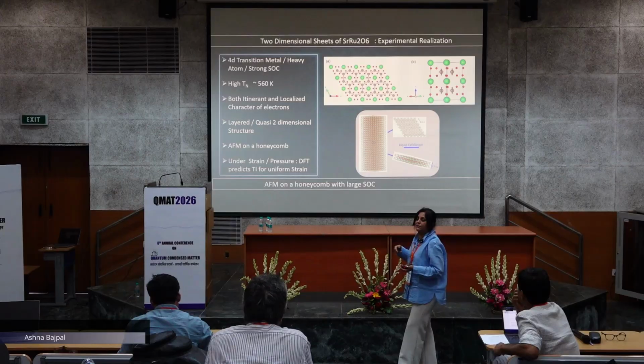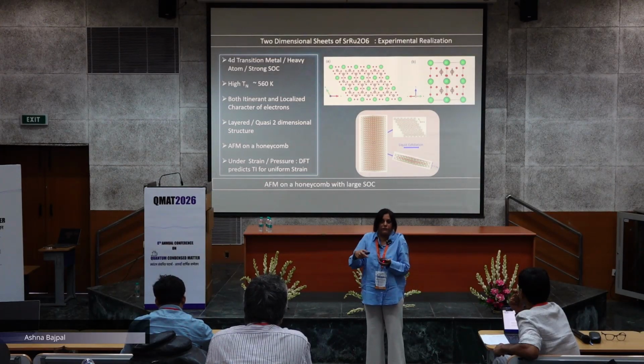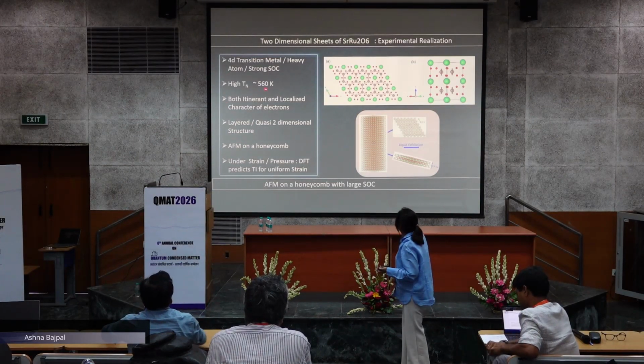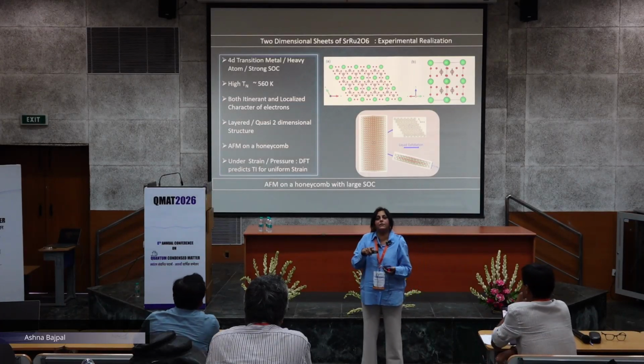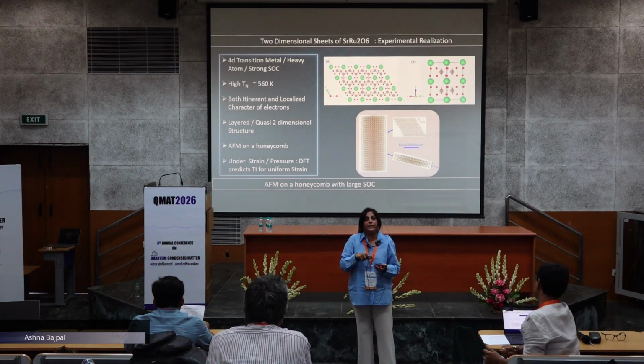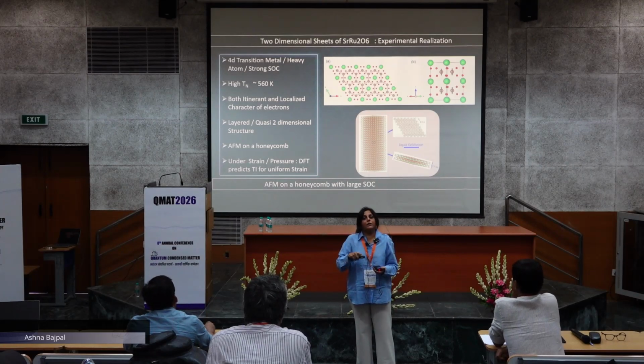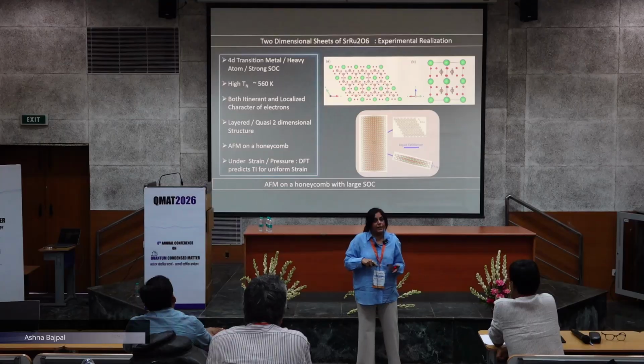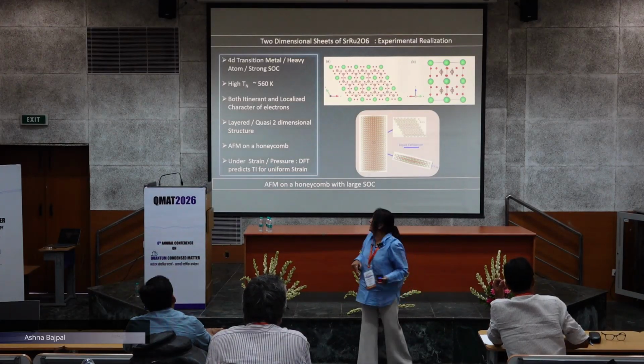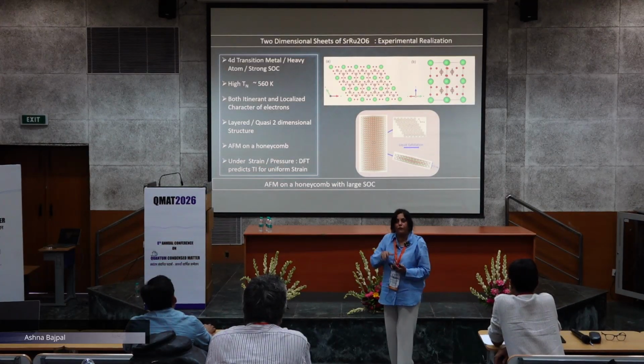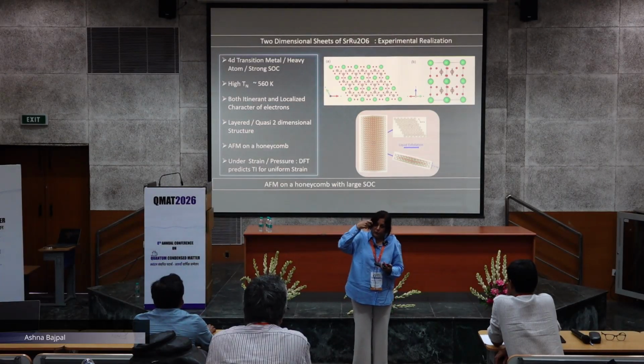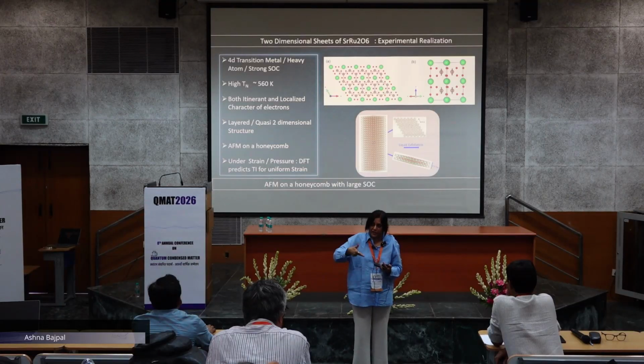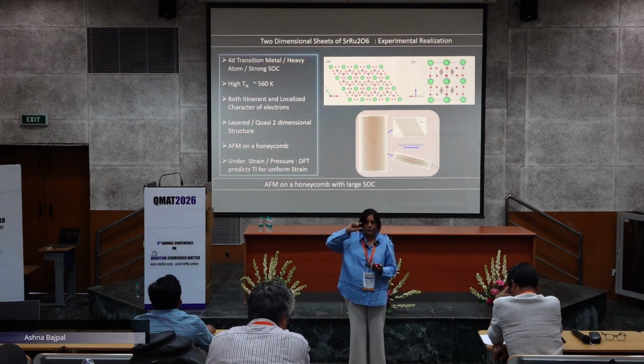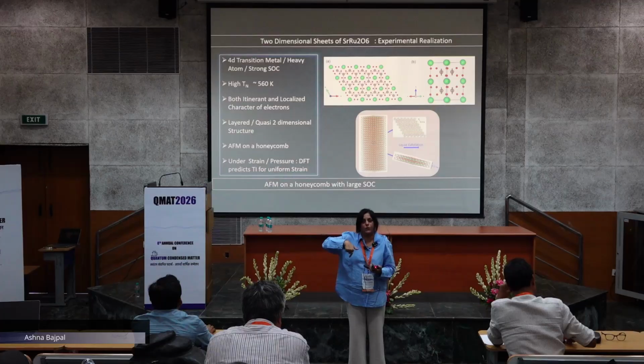Here, again I will remind you why this system is interesting. One thing is that, unlike RuCl3 and Na2IrO3, the TN is very high. It is one of the rare 4d based systems with very high TN, though it is less explored. TN is 550 Kelvin, which is very high, which is one good thing. Then you have a lot of tunability in terms of doping. We have done both electron doping, hole doping, strain; we have played with the Sr layers as well as with the Ru.